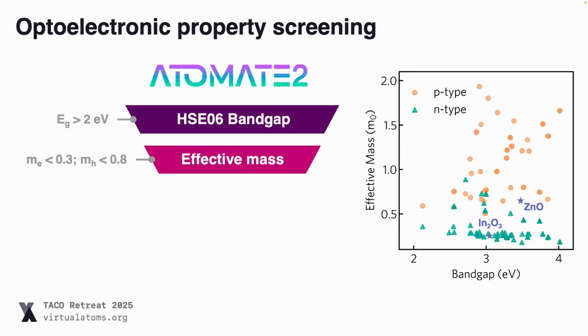And this is just a distribution of the 600 odd materials that we had before. You can see that this is the filtered materials. We've got band gaps going from 2 to 4 eV and a whole range of electron and hole effective masses. And this is just comparing them against some well-known TCOs like indium oxide or zinc oxide, and we have some comparable materials there.